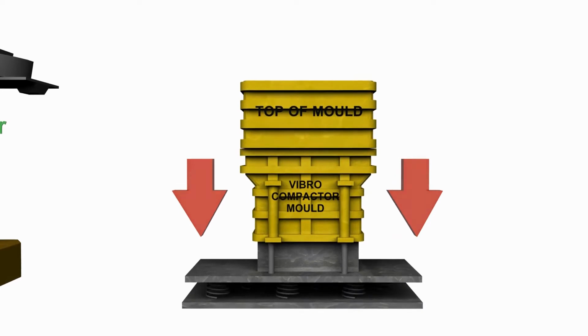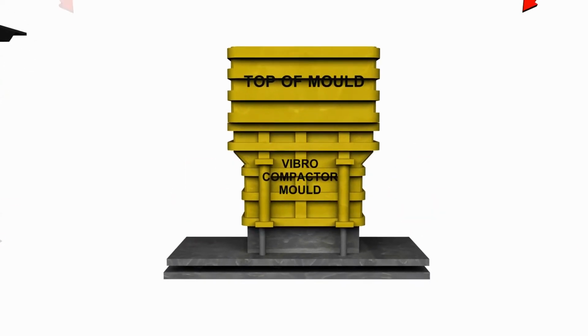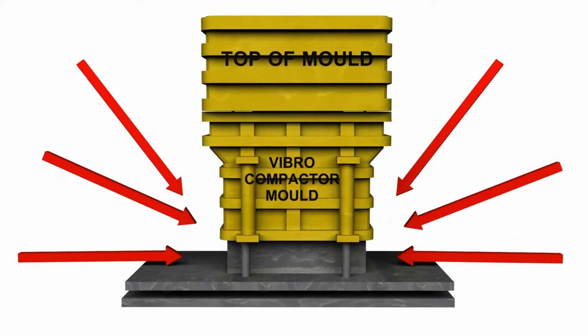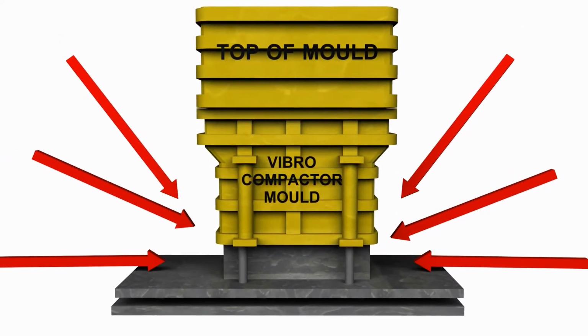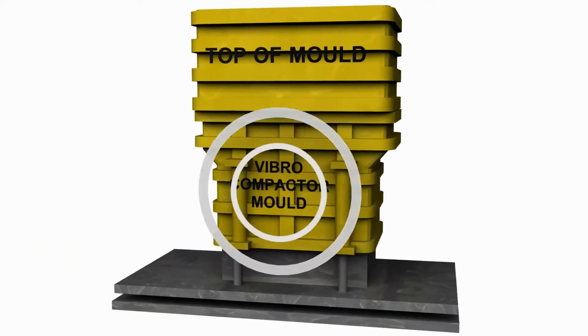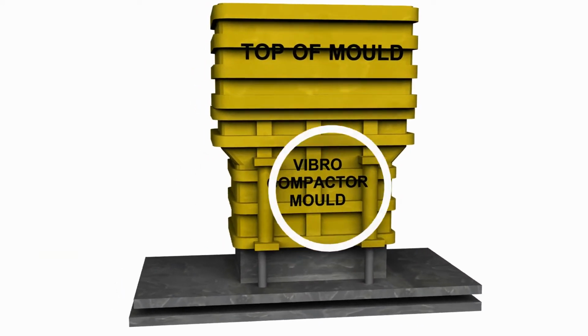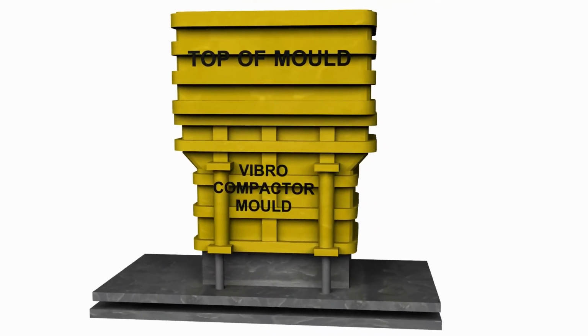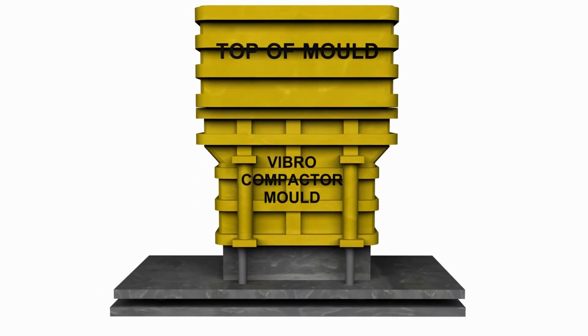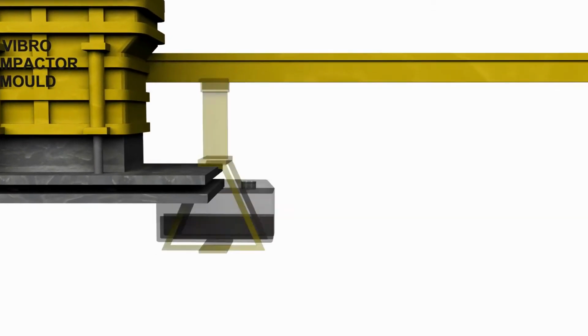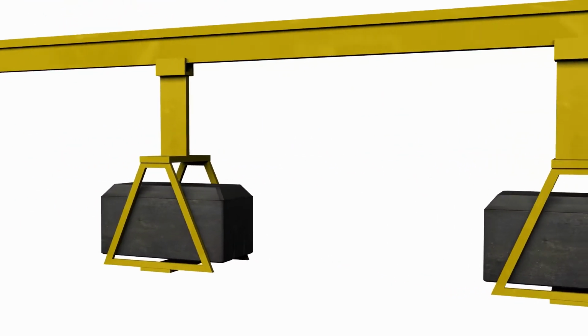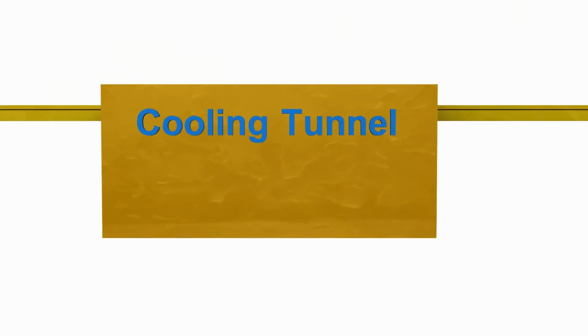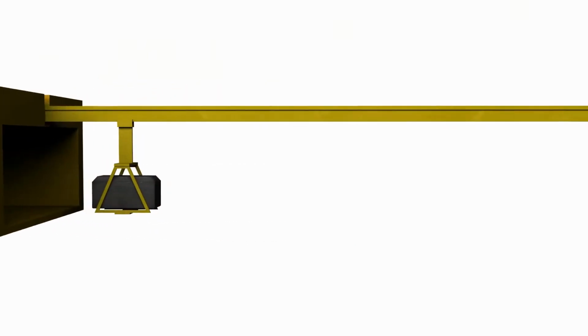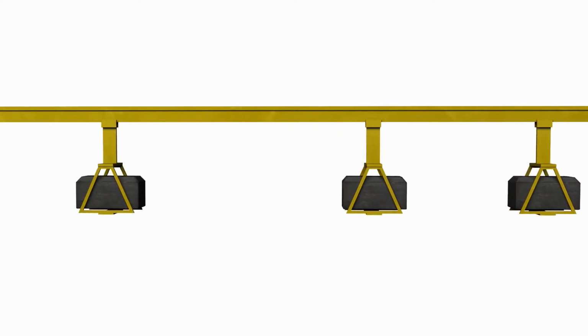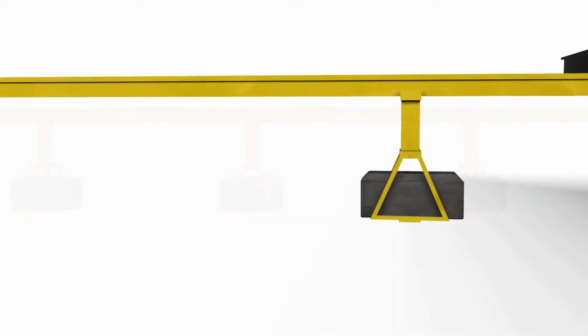The top section of the mold then descends, exerting enormous pressure onto the paste mix within the mold. At the same time, the mold is vibrated, which facilitates consolidation of the coke particles within the mixture. At the end of the process, the mold and the base separate, the anode is ejected and passed through a cooling tunnel where it is sprayed with water. The green anodes, as they are termed, are now ready for baking, a process which imparts strength and improves the electrical properties.